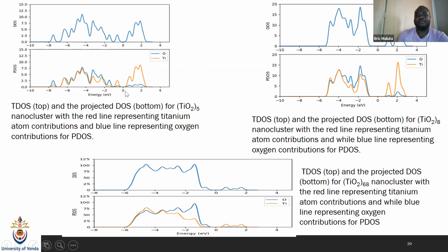And this other one here is for the TiO2 5 nanocluster. We have the TiO2 8 nanocluster on my right, and then the TiO2 68 nanocluster. Then you can see how the oxygen and the Ti elements contribute when we have the clusters. And just there, next to the zero, that's where we have our band gap. And as seen from the other surfaces, when we introduce other foreign elements, or when we dope with non-metal or metal, then we are also reducing the band gap of these clusters.